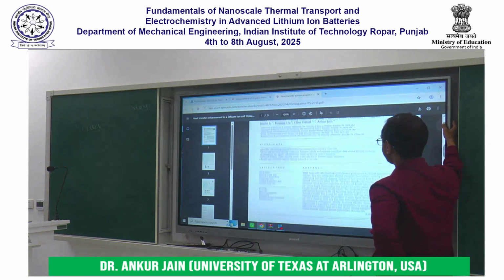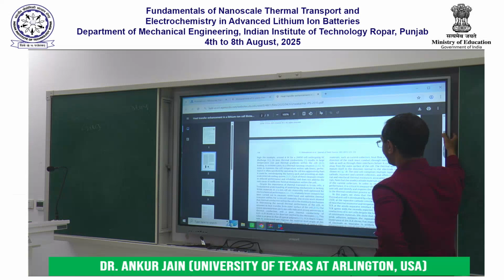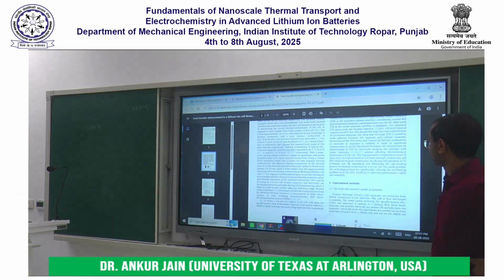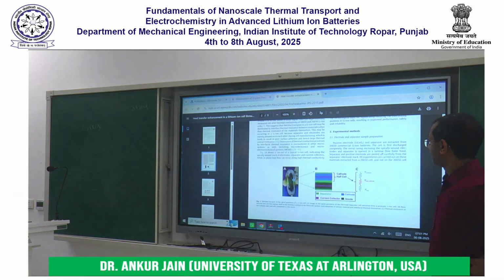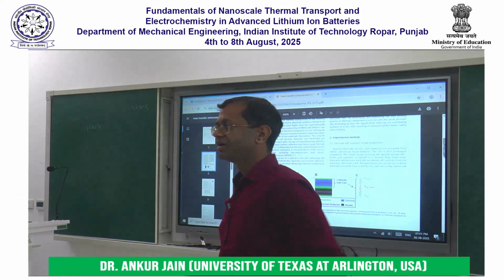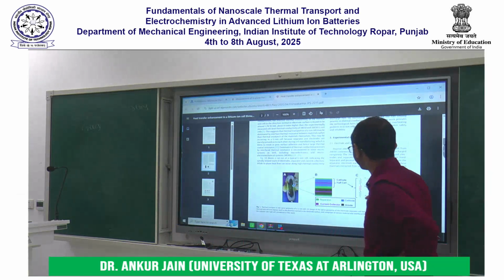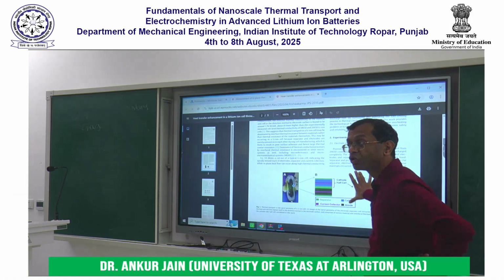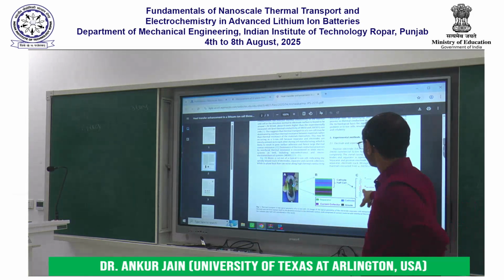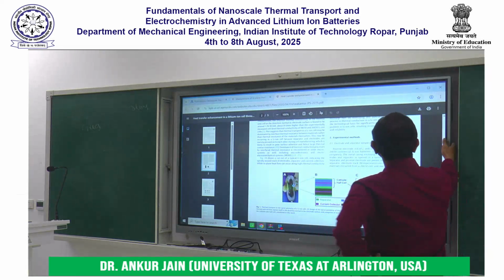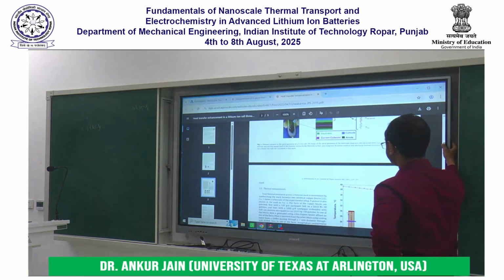So in this paper, we started by providing a justification for why these measurements are important, okay, and then we basically made the argument that I was making on my slides, that if I want to measure the resistance between the separator and the cathode, it is basically 3 resistances in series. If I measure 2 of them separately and I measure the total, then I can just subtract them out to find out the interfacial resistance. So to do that, we designed a very simple experimental setup